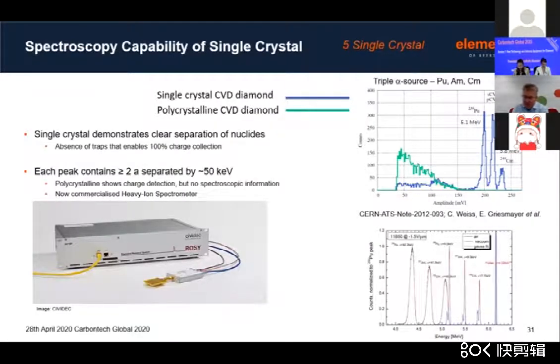And the key thing that this can now do is that you can exploit the drift of electrons through the material. And if you use a different radiation source, you can look at the energy, because how much energy the radiation has depends on how far into the diamond it will penetrate before it generates a charge. And by measuring the drift time through the material and drift velocity, you can resolve in single crystal diamond these energy peaks, i.e. you've got a spectrometer capability that you don't have in polycrystalline materials, where you detect the radiation, but you don't know anything about the energy of that. Again, that's been commercialized, particularly in the high energy physics community and also in the neutron community, as spectrometer devices.